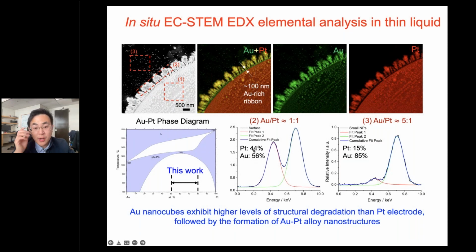So really what we're observing is the formation of the bimetallic alloy in a region which is typically not accessible to chemical synthesis, in this white region, which is supposed to be phase immiscible. But yet we can push the formation of this bimetallic alloy, and this is only possible because we are driving a highly kinetic process of cathodic corrosion.